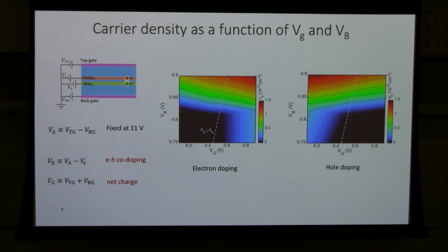at relatively small bias voltage, the conduction band and the valence band do not overlap. So in that case, you can create only electron doping or hole doping, but not at the same time. So what you can see is with this gate voltage, you can create electron doped layers. And in this range, you will create hole doped layers, but there will be a middle part where you have no electron or hole doping.